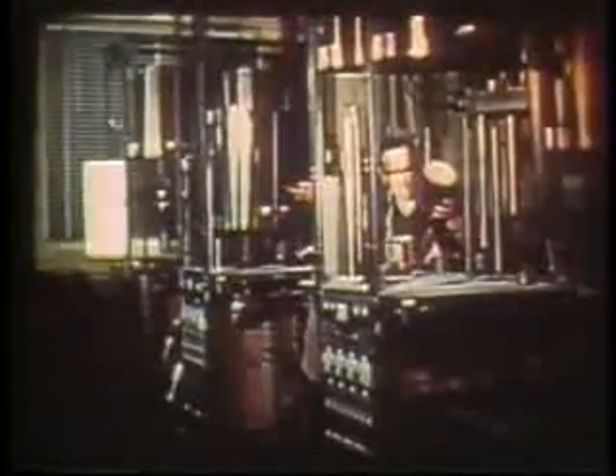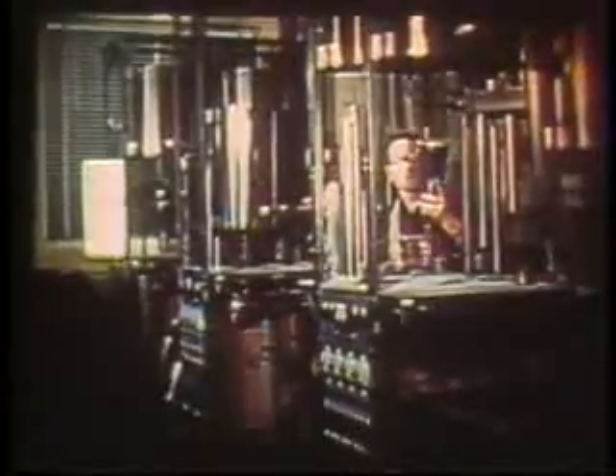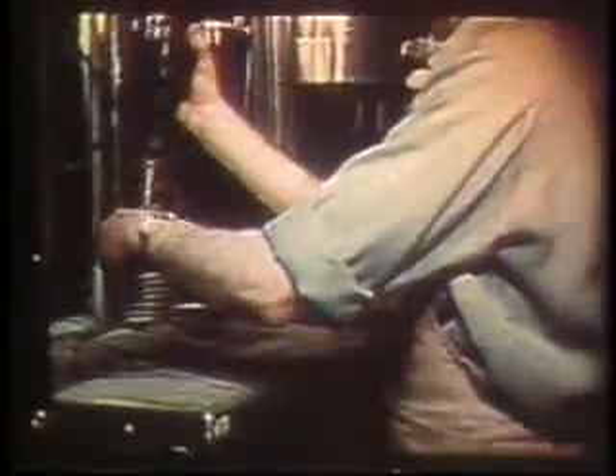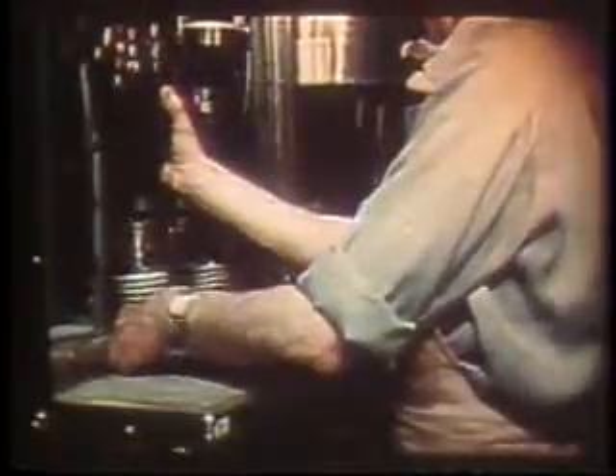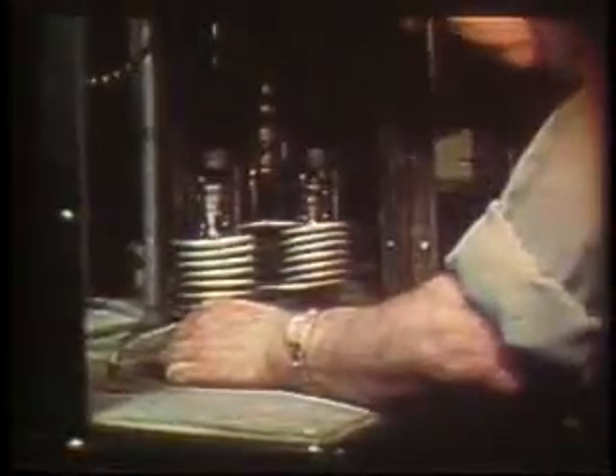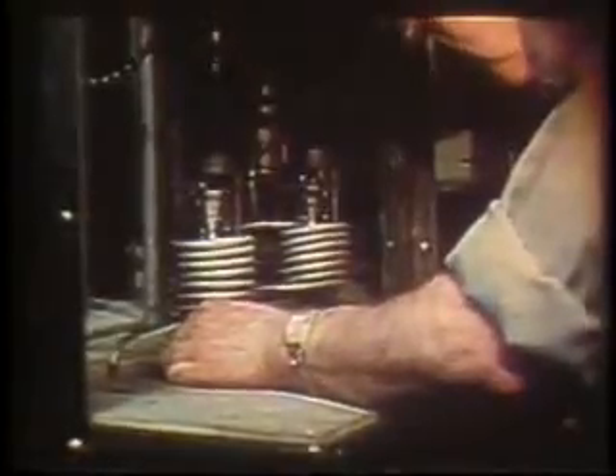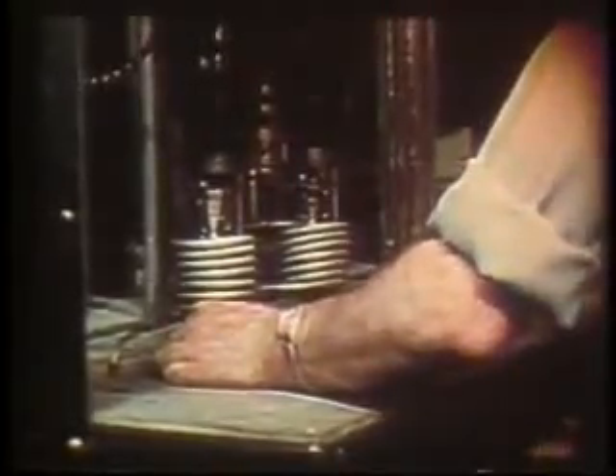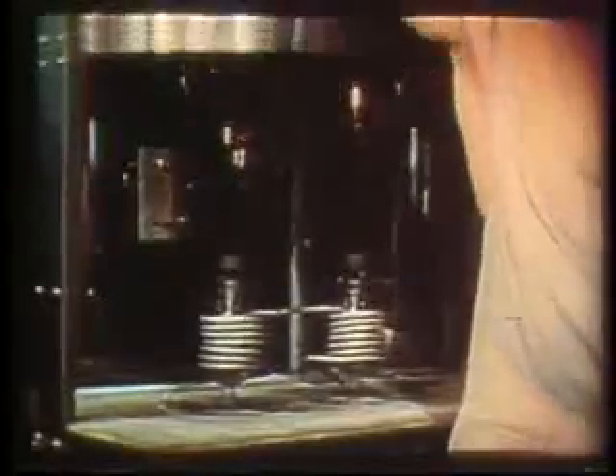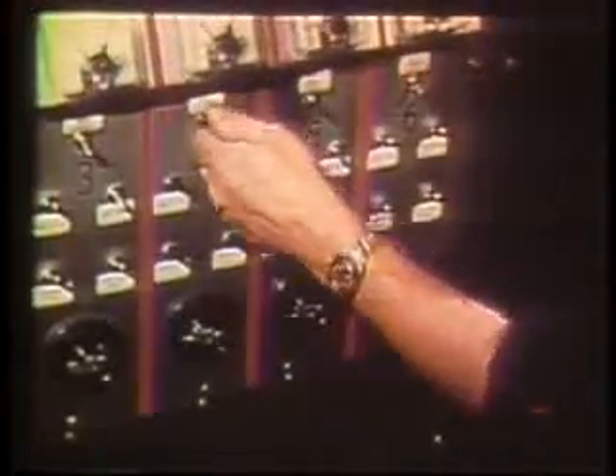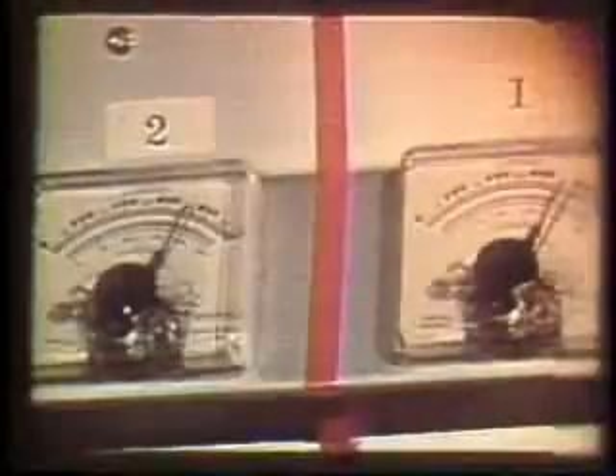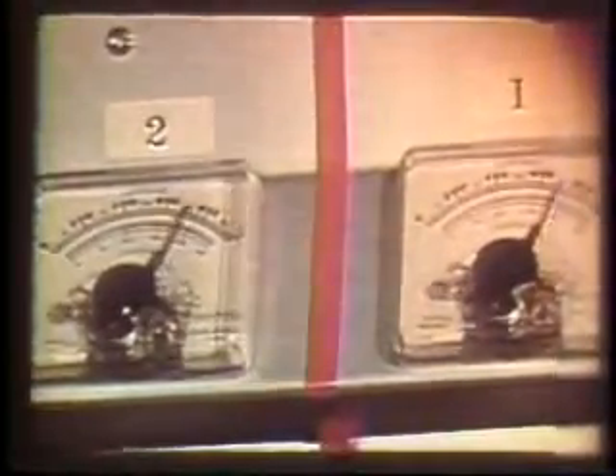The tube is now ready for the final, but one of the most important processes. It is sealed to the vacuum pumps. As the tube is being exhausted, the metal parts are heated with radio frequency energy from an induction heater. This helps to drive out gas trapped within the pores of the metal. An oven is lowered over the tube. This will heat the complete tube to a temperature just under the softening point of the glass. The temperature must be very accurately controlled. Only a few more degrees and the bulb would collapse. If a relay should happen to stick, we get a tube that looks like this.